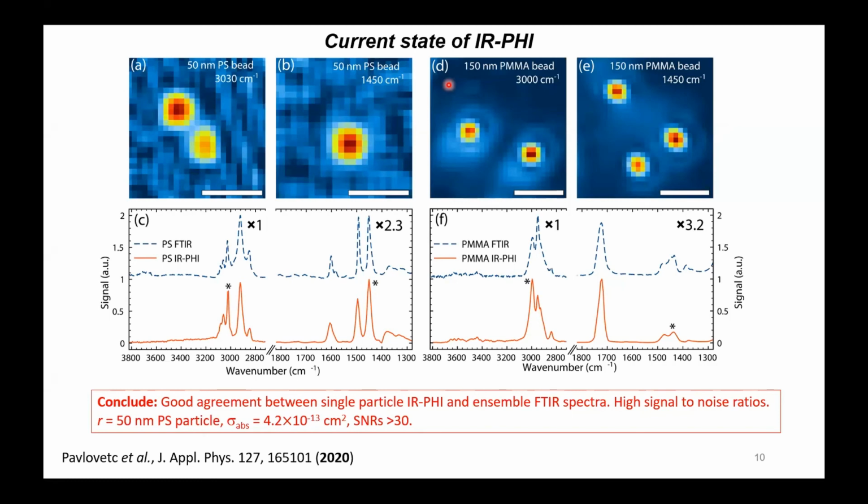This sounds bad, but I assume it's a small contribution from air: if the particle is heated to, let's say, 50 kelvins above room temperature, it's going to change the refractive index significantly enough to measure it. I'm usually always surprised to see them because the thermo-optic coefficient of air is 3 orders of magnitude smaller than that of polymer. So this is a lingering question. Okay. Nice.